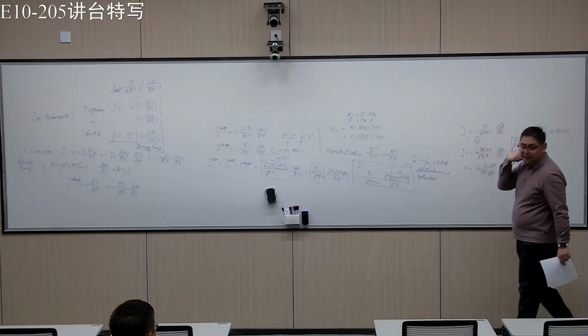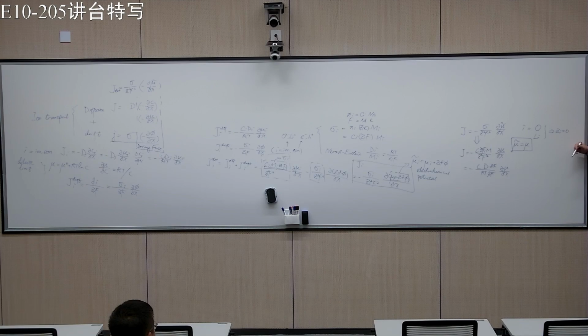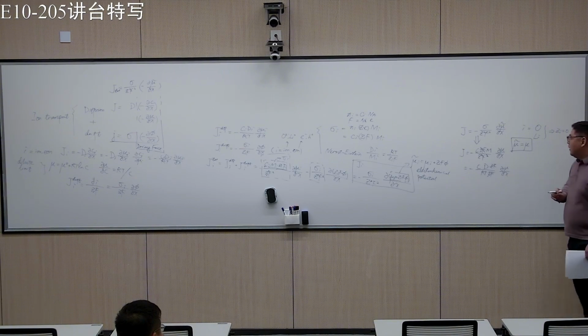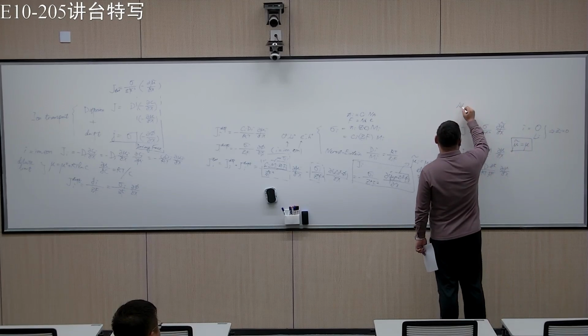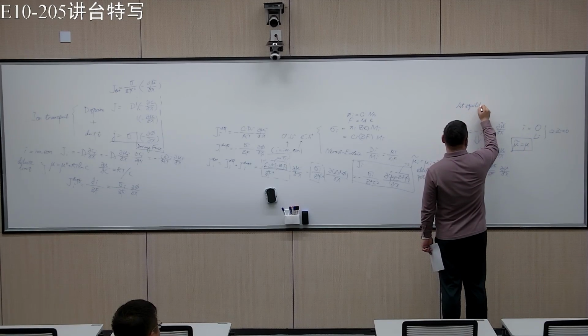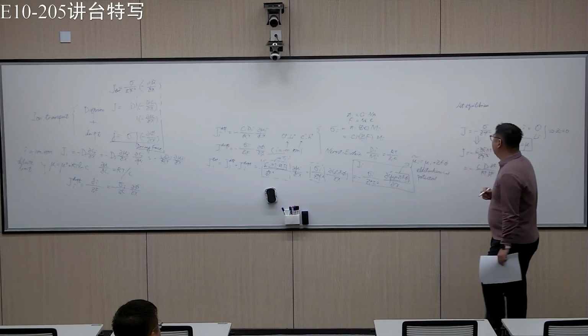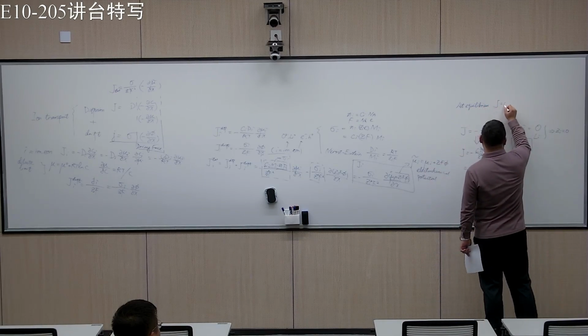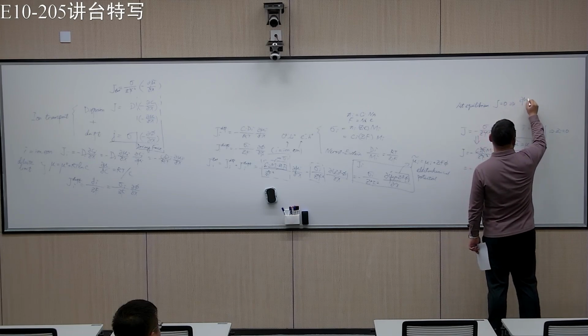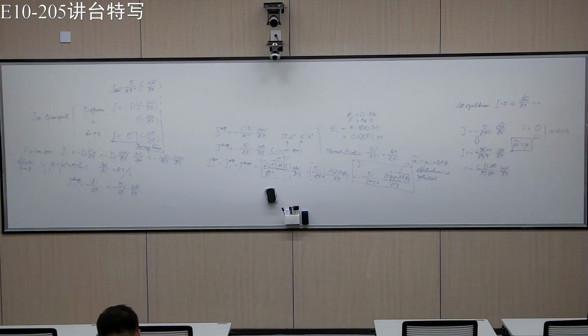Okay, which means that, so this is a kind of difficult way to show. So this should apply to any system, whether you have only diffusion or you have diffusion and drift. So of course, we know that if we reach equilibrium, at equilibrium, then the flux should be 0. Then the condition gives you partial mu i, partial x, it's basically 0. So this is basically the equilibrium condition.